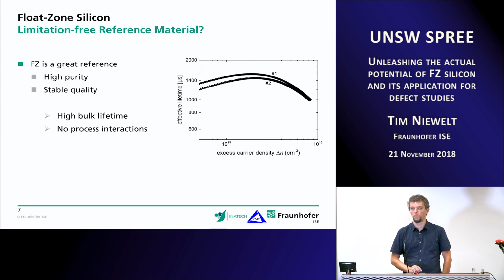Then experiments with a passivated sample. I guess this is a p-type 1 ohm centimeter sample. You of course have some variations in the lifetime that we get. So here's a lifetime plot for 2 samples, and we have some variation with just processing issues. However,